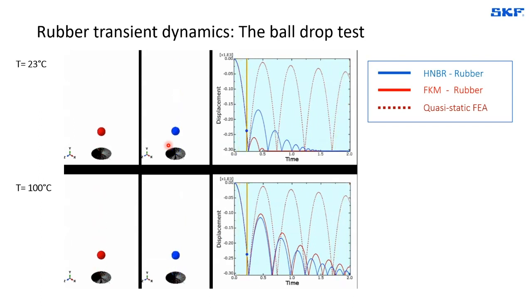It is simply the ratio of the loss modulus over the elastic modulus of the rubber in that condition, commonly called the loss factor or the tan delta. And relating to this, we can then predict, after having done the right material modeling, why the HNBR material is reacting in such a way versus the FKM material. What is also interesting is to pay attention to what a quasi-static typical finite element analysis would provide: basically no difference between the balls, telling us that we definitely need to take into account the transient dynamics of the rubber if we are to be able to predict properly the sealing system performance.